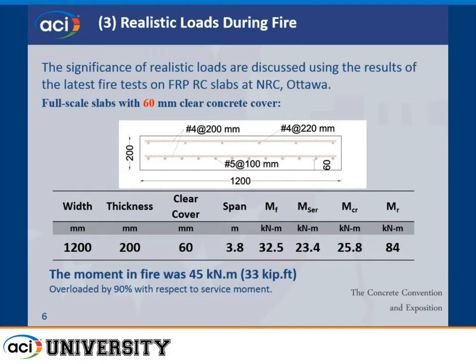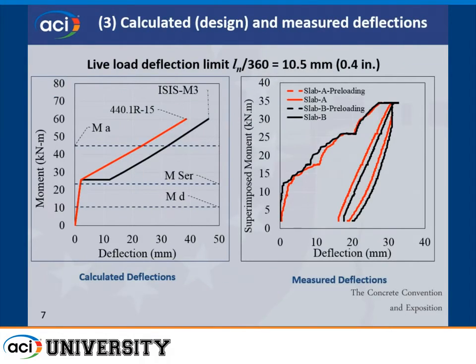The reason for that has to do with the expected service moment. So you see what we're designing for this, that our actual service load is much, much lower than this, and actually technically below the cracking load. So what happens in FRP reinforced compared to steel reinforced is that your design is governed much more by serviceability requirements, both deflections and crack control.